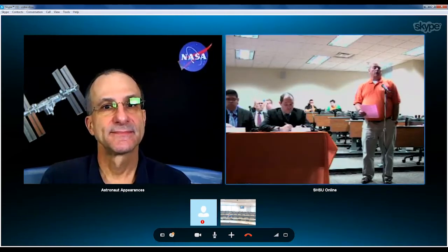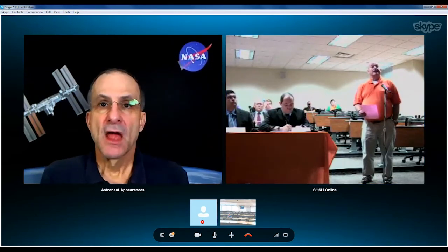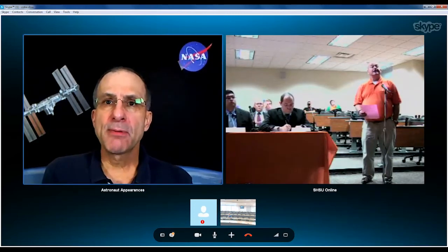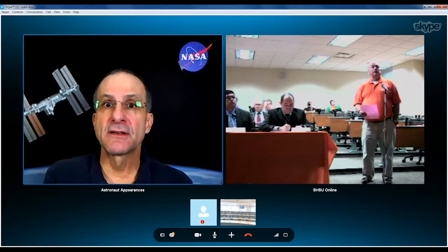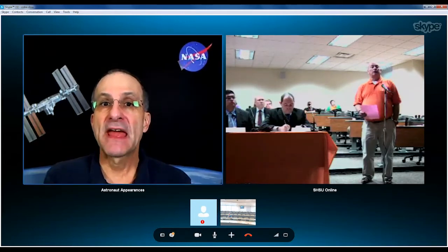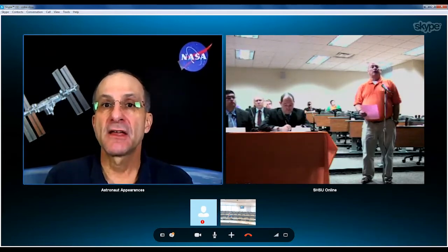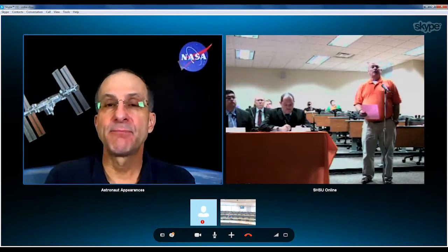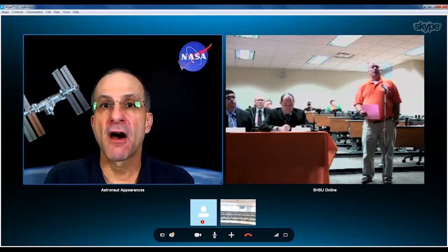What about an environment where either hydrocarbons or water were present? Would there be any problems with it? Probably not. You'd have to look at the borate glass compounds, and again, you can formulate this. The idea is that you have a silicon-based oil with a number of other compounds that you add to it, and you can add borate glasses. I added the borate glass specifically to make a lower melting point material that would wet the leading edge of the space shuttle.